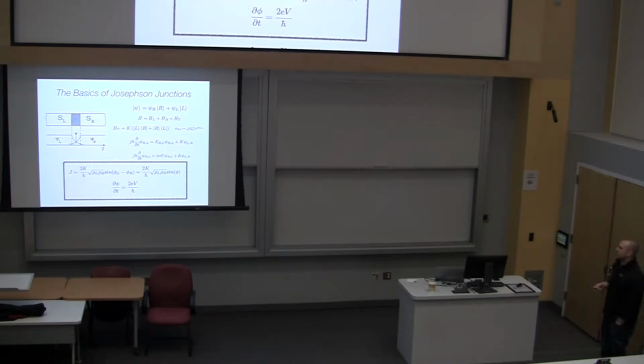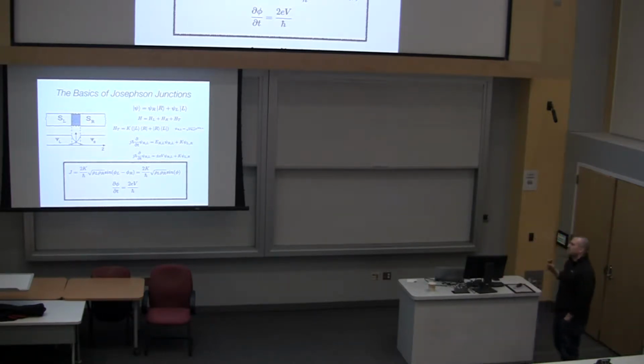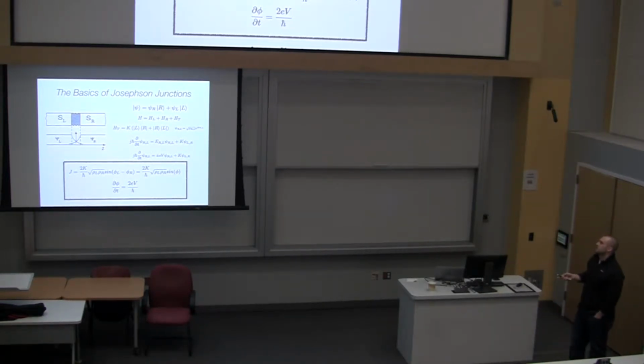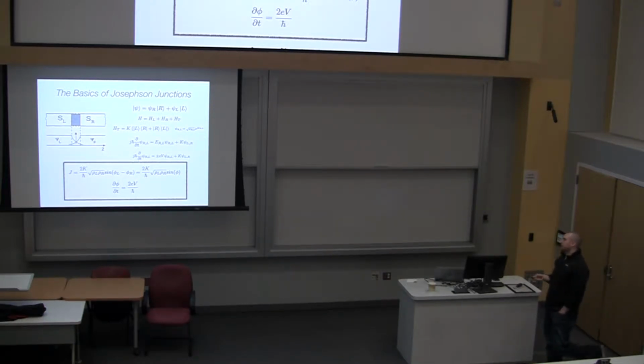The simplest way to back out the properties of this material is to use a two-state approach where you have a wave function on the right and left, and there's some coupling, this transmission or transfer Hamiltonian, that allows you to hop a Cooper pair from the left to the right or the right to the left. So basically by writing the order parameter as the square root of the density of Cooper pairs times some phase, separating out the real and imaginary parts of the time-dependent Schrodinger equation, and allowing for a voltage difference to exist between the left and right lead, if you solve these equations, you come to two of the most fundamental equations that govern the behavior of Josephson junctions.